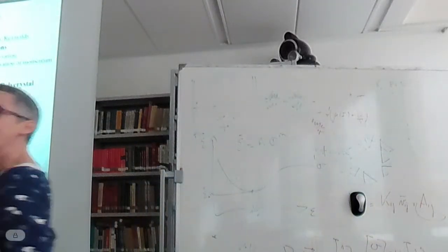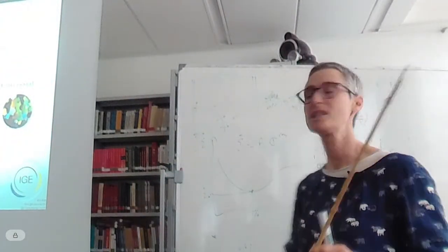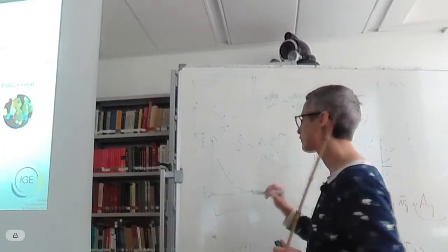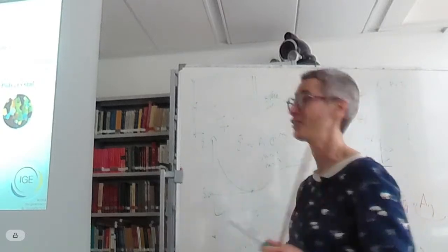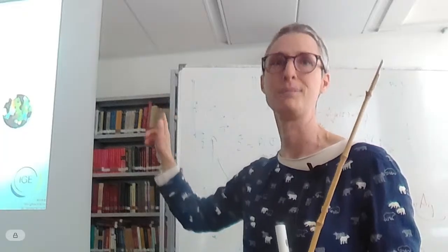Actually, is that the law that relates to deformation? And in large-scale modeling, this is what has been used. So in the simpler large-scale modeling, they consider that n equals 1. From the lab, we know that n equals 3. But then when we are in conditions of very low stress, very low strain rate, big question mark.